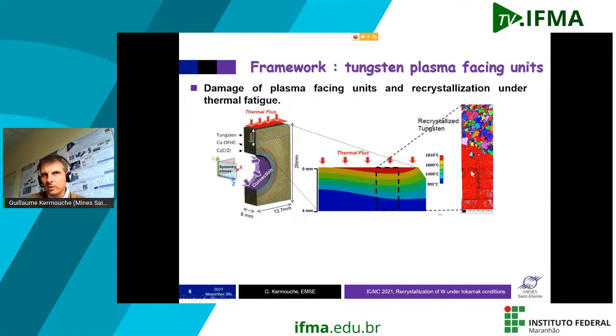So to understand that, you have to consider that when the material is red, it means that this is the raw material. It has been, I would say, warm rolled, in this case for tungsten. So there's a lot of deformation. That's why it's red. Okay, and here you have just some single color, and so that means that the grains are perfectly recrystallized. So there is a recrystallization that happens in the near surface after a given number of cycles.